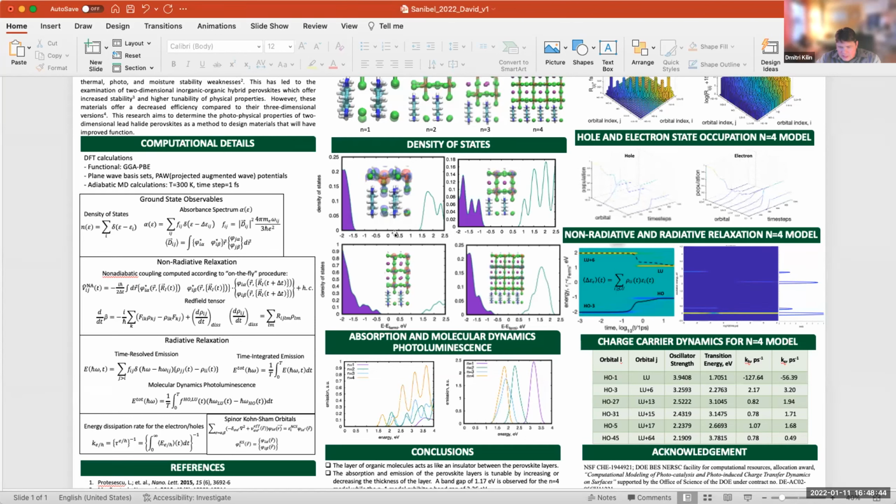First, the interaction of electron and hole, so formation of a bound state. When the excited electron and excited hole attract each other, the band gap energy effectively gets smaller. Second, upon photoexcitation, the interatomic distances rearrange, and typically that also leads to the band gap becoming smaller than in the absorption.